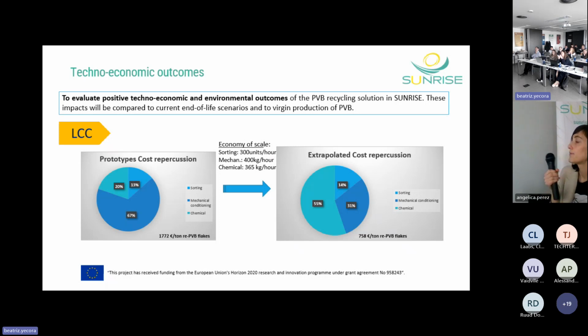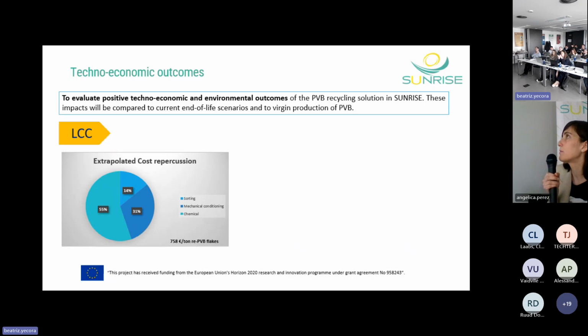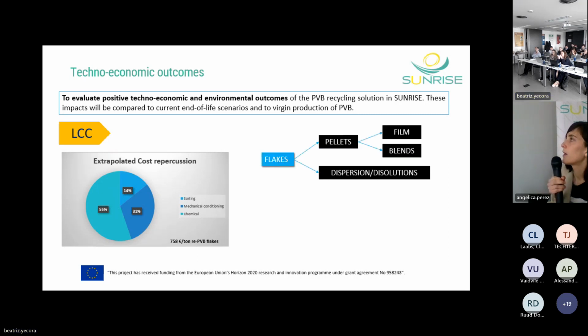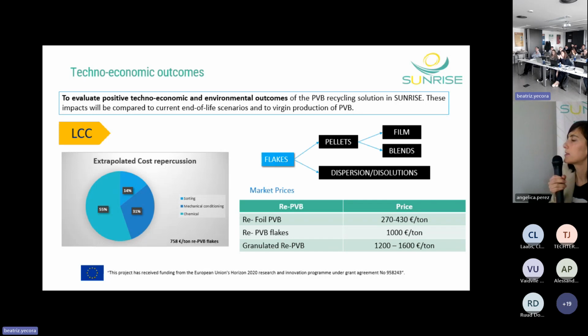Also, thinking that in this case, the chemical step could be the one with the highest repercussion. But we are at prices that are comparable with the market of PVB flakes. So these are the market prices for foil PVB. For flakes, we are finding prices in the market around 1,000 euros per ton. And these granulated recycled PVB are higher. Of course, these granulates are not for film applications.